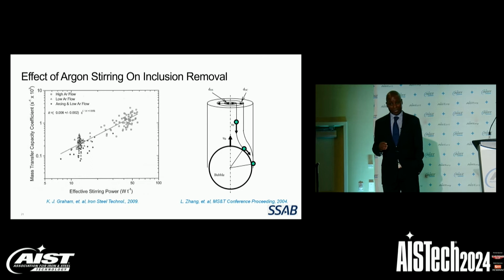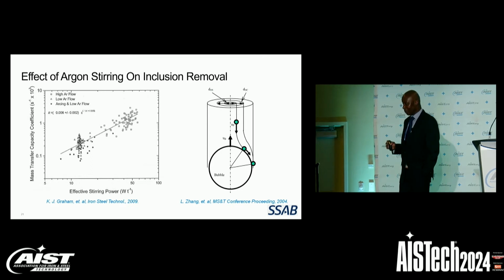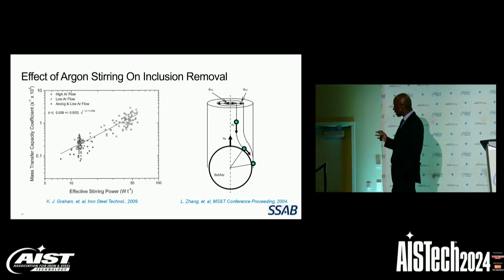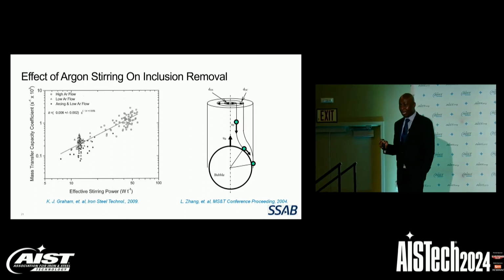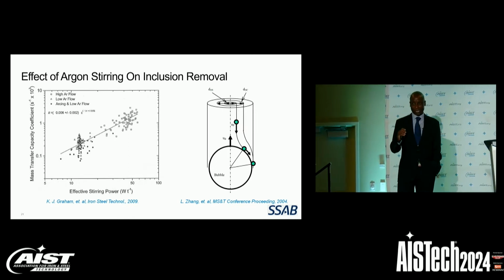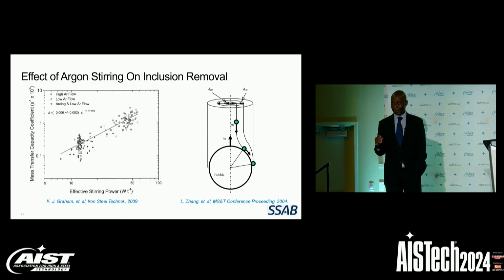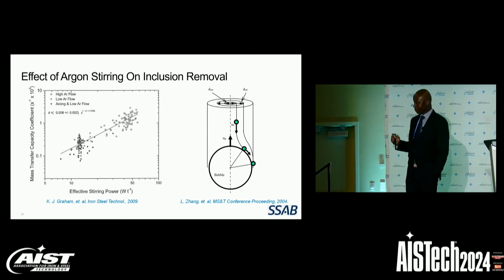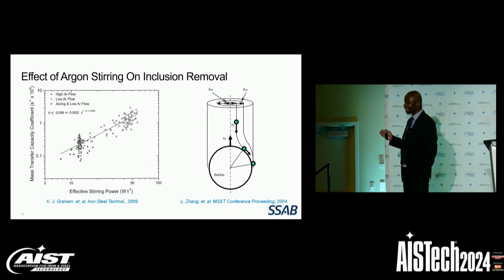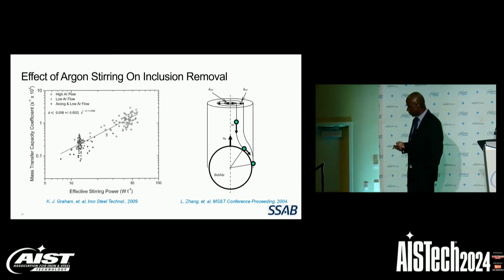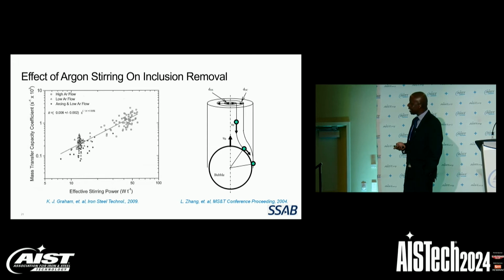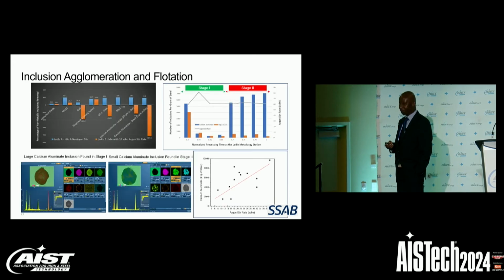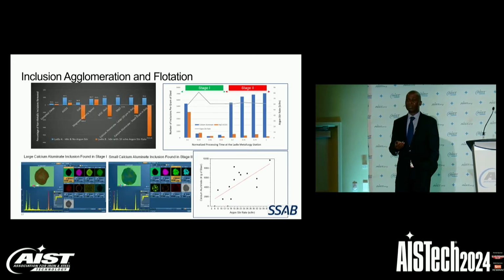The reason for that is that the size of the argon bubble is significantly larger than the size of non-metallic inclusions. And also, the argon bubbles are significantly lighter than non-metallic inclusions. So the upward velocity is very high. So if inclusions get attached to those bubbles, that will enhance their flotation from the liquid to the slag-metal interface. But we decided to investigate this phenomenon further by doing experiments.